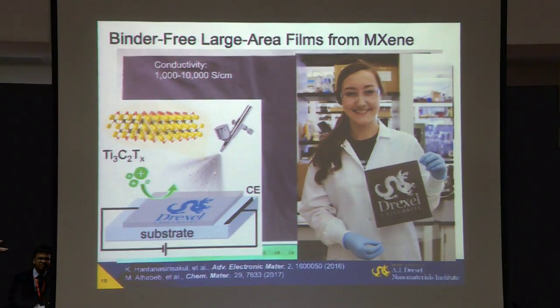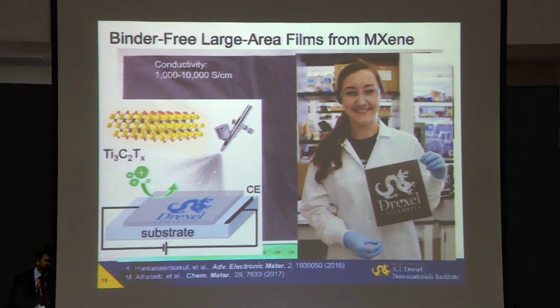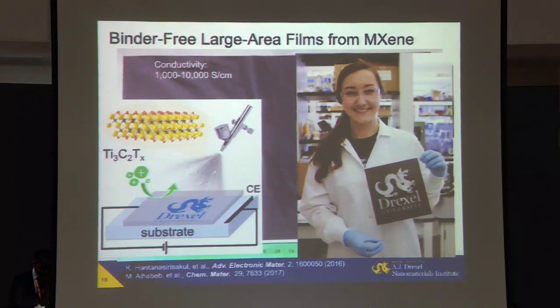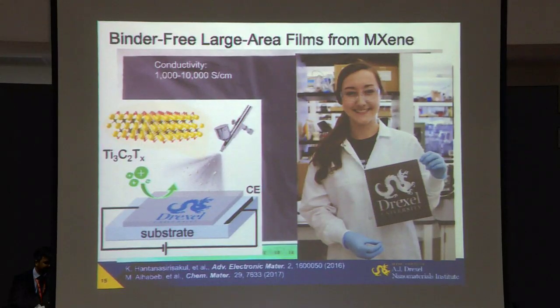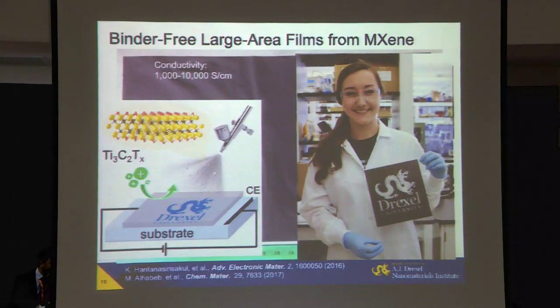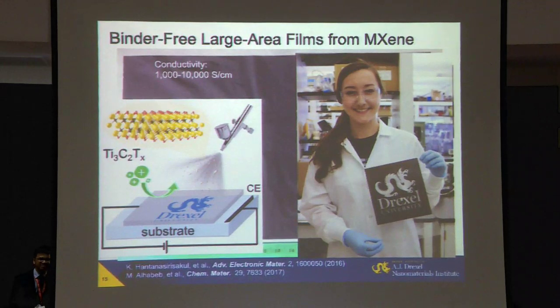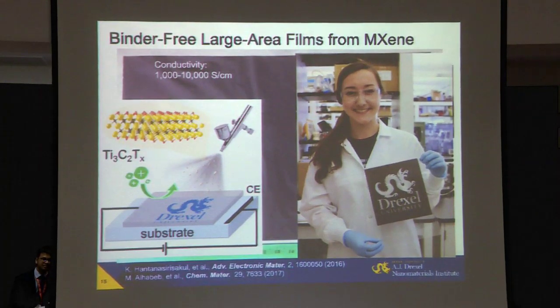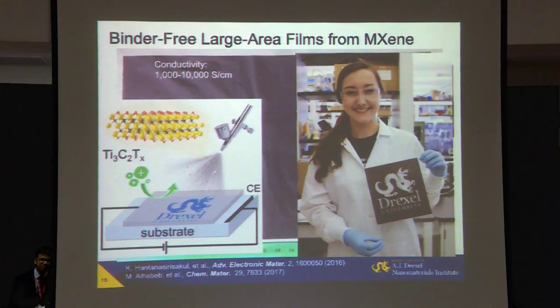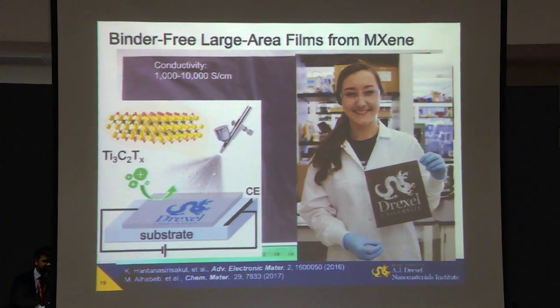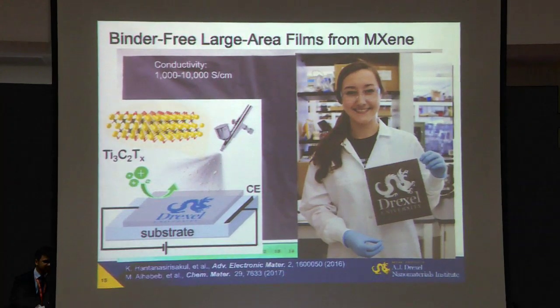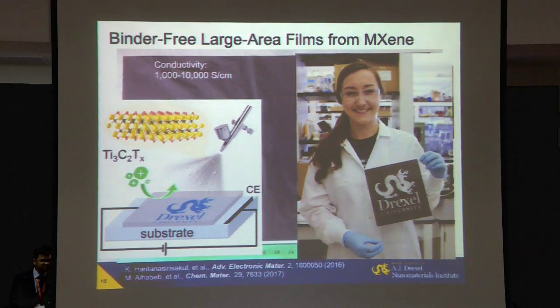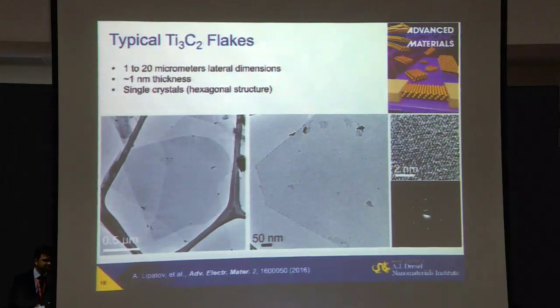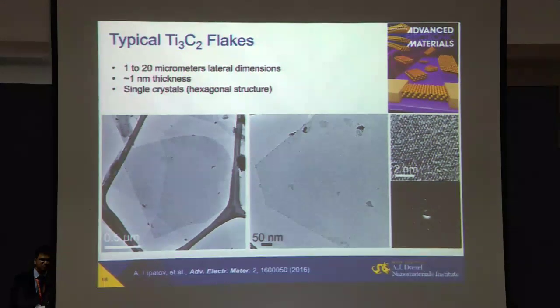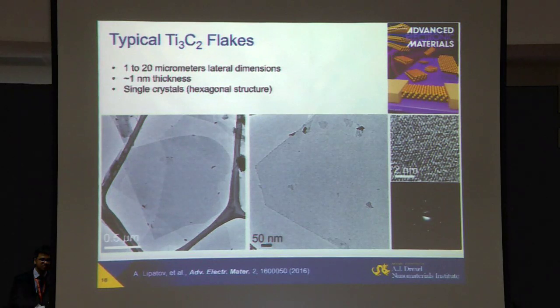You see, we use ceramic powder. We use cheap acid, for example, like HCl and a fluoride salt, like lithium fluoride here. And we use a $20 spray gun, I'm pretty sure in India it's probably even less expensive, the same you would basically use to paint walls or paint something else in your house, to produce nanomaterials with conductivity exceeding pretty much any two-dimensional material solution processed that is known here. And this again shows that you don't need some kind of super sophisticated equipment to do novel work and make novel materials here.